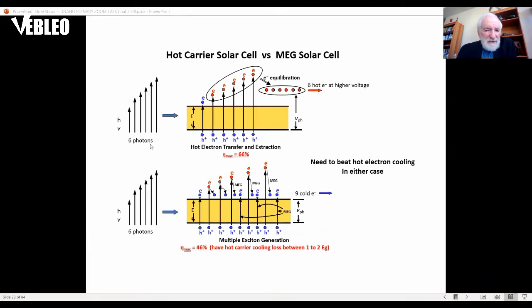The ultimate efficiency is a little bit lower than the Shockley limit or the hot electron extraction, because in the hot electron extraction, you use all the hot electrons, and even the cold ones get heated by the hot ones up here. There's some intermediate temperature describing these hot electrons, and you extract them all at a higher voltage and get that higher voltage. But in impact ionization, or MEG, multiple exciton generation, as it's called in nanocrystals, you have to get to twice the band gap before you get the multiplication. So photons between 1 and 2 times the band gap will only create thermalized electrons, and you need to be twice the band gap in order to bring the onset of this process to get 2 electrons per photon, and that reduces the efficiency maximum from 66 to about 45.